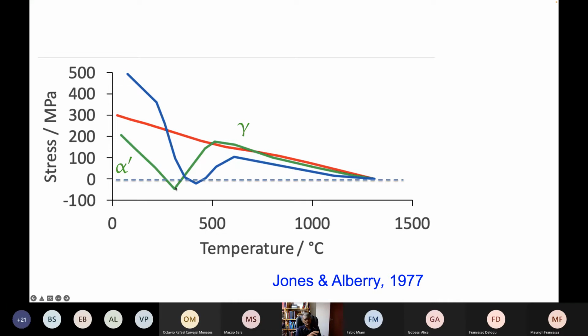All you have to do is move this point to somewhere along here. Okay, so cause the phase transformation to happen at a temperature of around 200 degrees centigrade, and all the austenite should be used up by the time you get to ambient temperature, because we don't want retained austenite left.